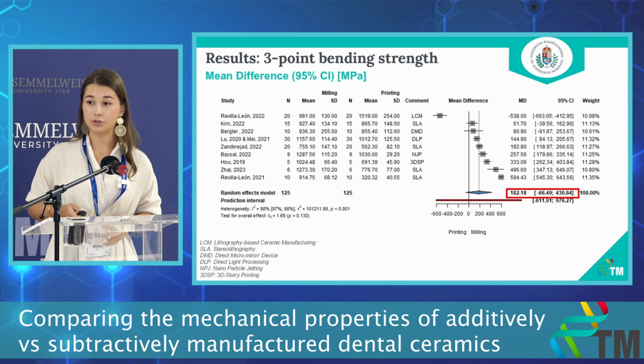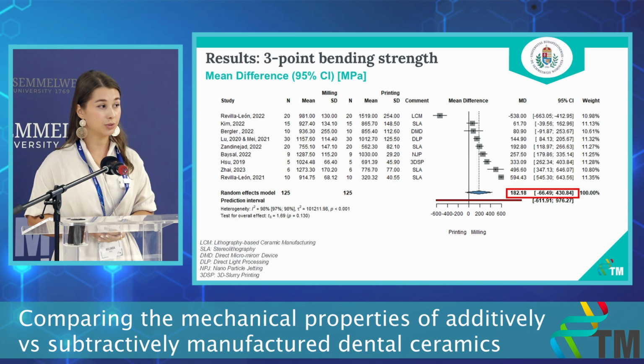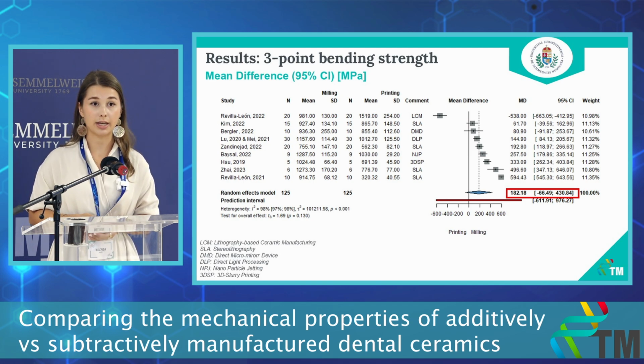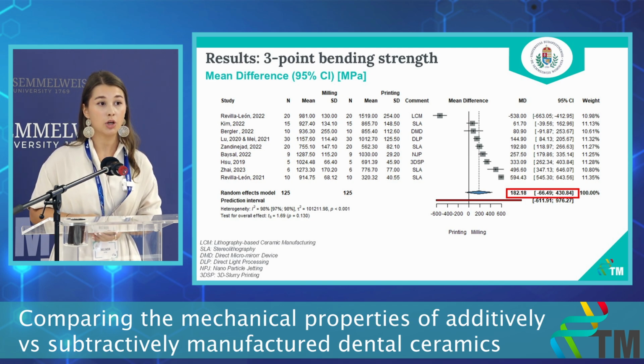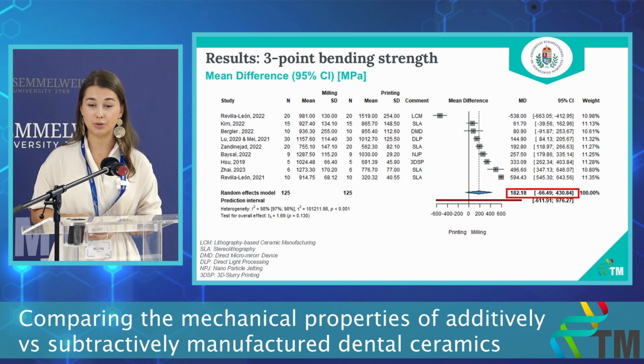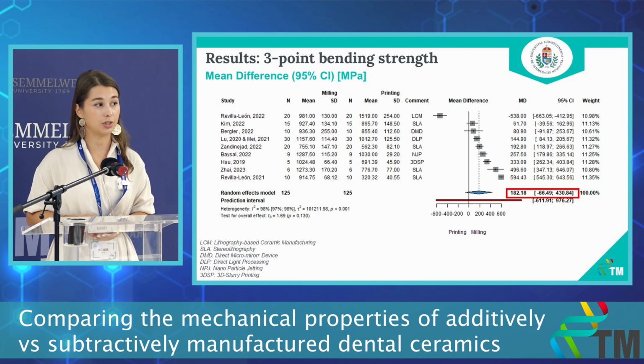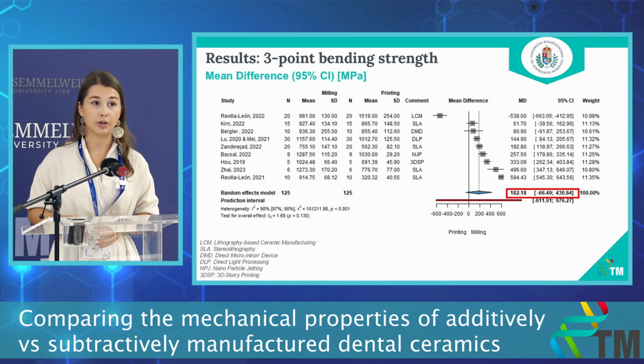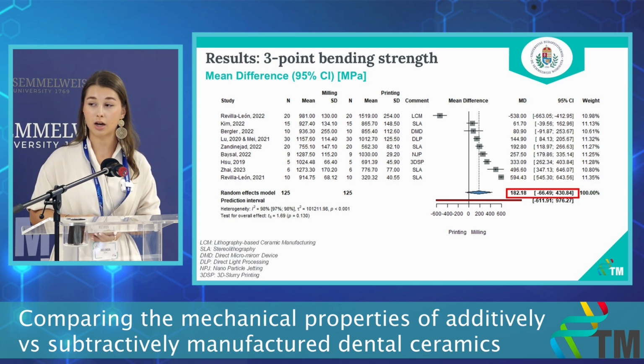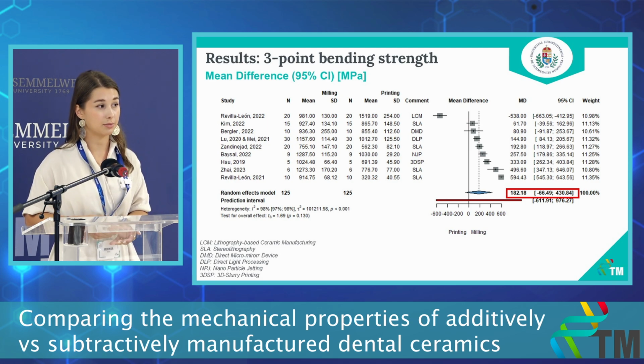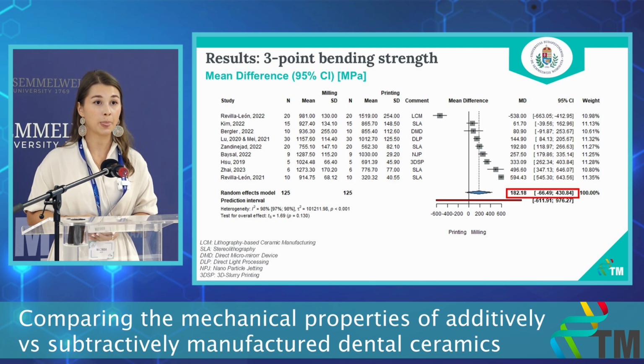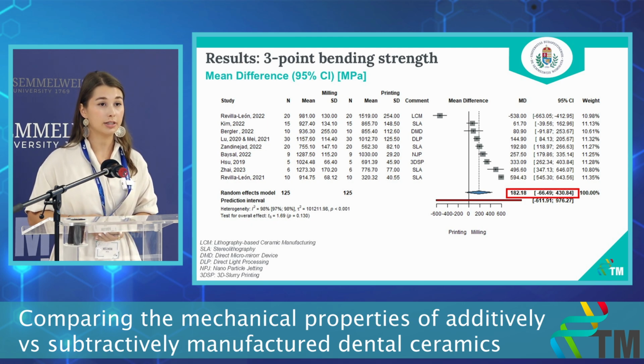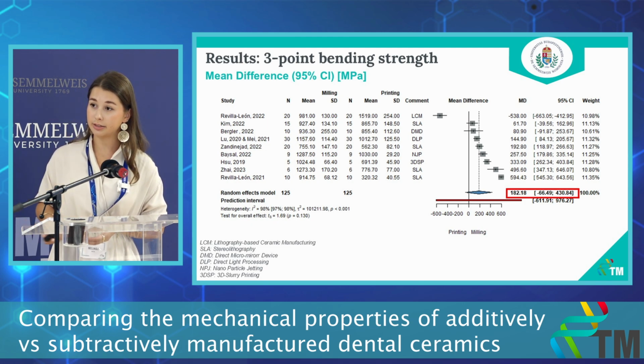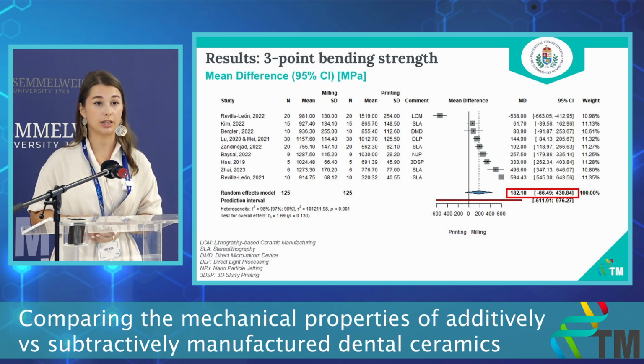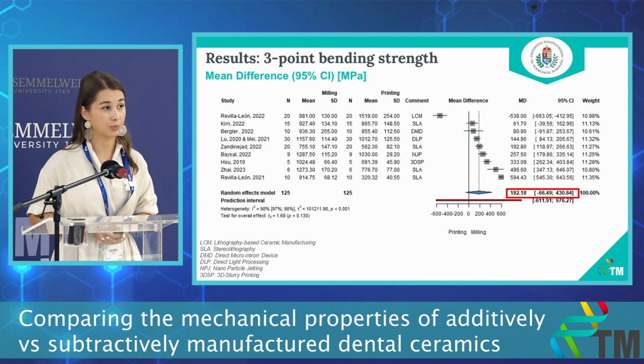Here you can see the details for our 2-armed studies. We included 9 in vitro articles that had similar weight on the outcome. You can't unsee the big heterogeneity, which is due to the fact that these articles use different brands of zirconia, different printing techniques, as you can see in the comment section, and sometimes different specimen dimensions. Our outcome is mean difference, and if the article is on your right, then the milled material was stronger in the study, and if it's on your left, then the printed was stronger.